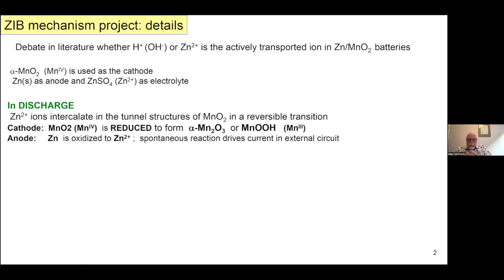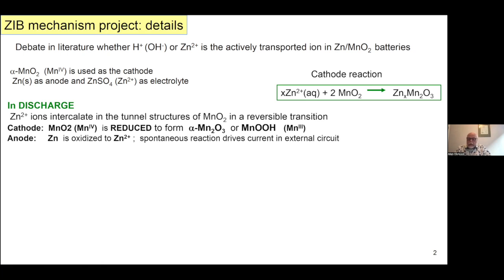So the hypothesis is that when you have a charged zinc ion battery, and it is used to discharge to drive a current in an external circuit, the MnO2 is being reduced because as the zinc 2+ intercalates, you reduce the manganese 4 to manganese 3. And simultaneously at the anode, there's oxidation of the zinc metal to zinc 2+. And so that reaction can be symbolized by that chemically, but of course it's split into 2 half reactions.